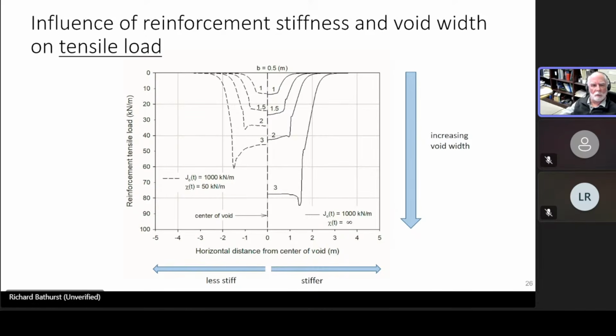So what you see here on the right-hand side, as the width of the void gets larger and larger from 0.5 to 3 meters, you can see that the tensile load in the reinforcement goes up. And I think that makes intuitive sense. But the actual magnitudes are sensitive to whether you have a soft reinforcement versus a stiffer reinforcement. So you can see that the tensile loads are less for the softer or less stiff reinforcement.